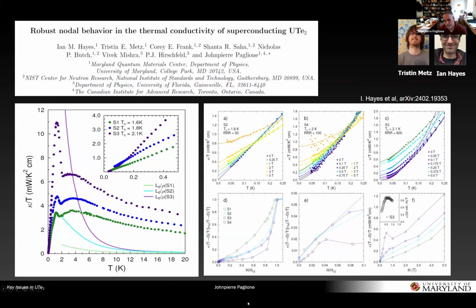Then if you take these extrapolations and plot them as a function of magnetic field, here we just do it normalized to HC2 in the low field regime, and just as raw data, you can see that there's a rapid rise at low fields for all the samples, including the highest TC sample. What I would argue is that the data we measured, especially in this sample here, is within the error bars of the Matsuda experiment. But we clearly show that there's a rapid rise and that it is a nodal superconductor.